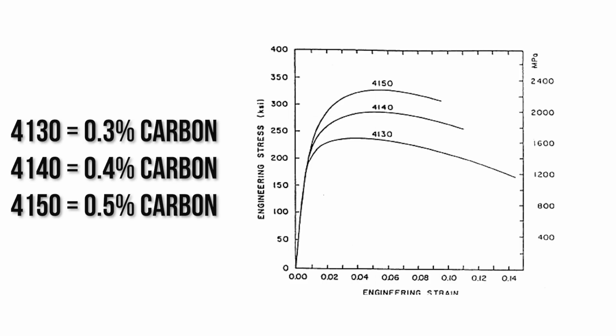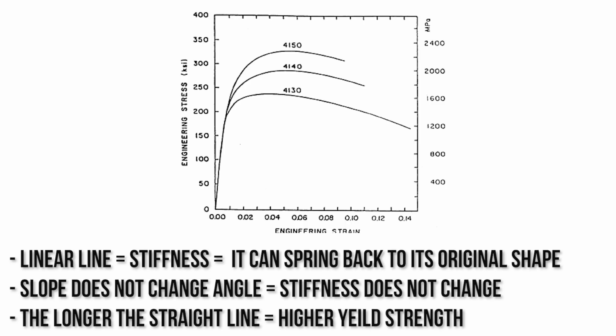What I have here is a graph of several different steels, with the only difference being carbon, and whilst it does get stronger, because this slope goes on for a longer period of time, the angle of the slope itself doesn't change, which means that the material itself doesn't get any stiffer. And it's worth stressing again, the only part of the diagram that we're really interested in here in terms of stiffness is that straight line. That straight line is stiffness. And the reason for it is that any stretching or elongation or any force that's applied, once you remove the force, it will spring back to its original shape.